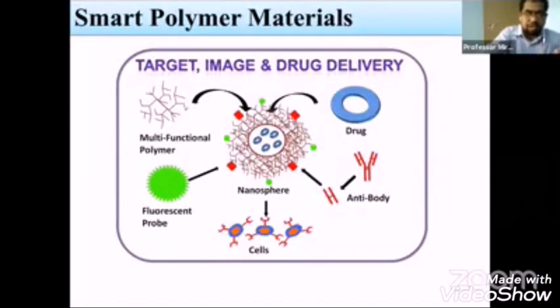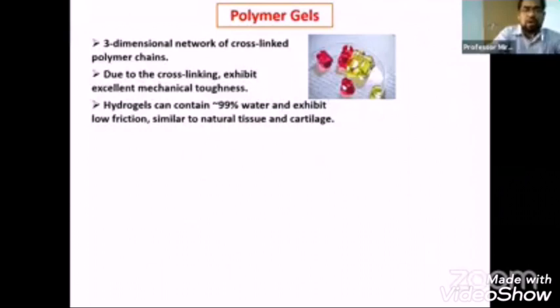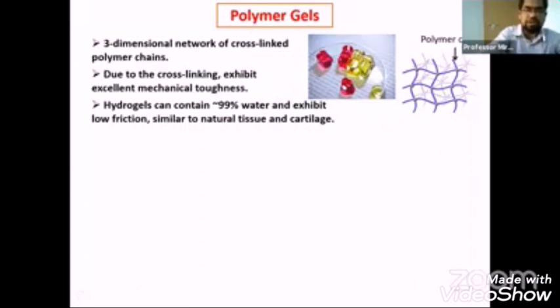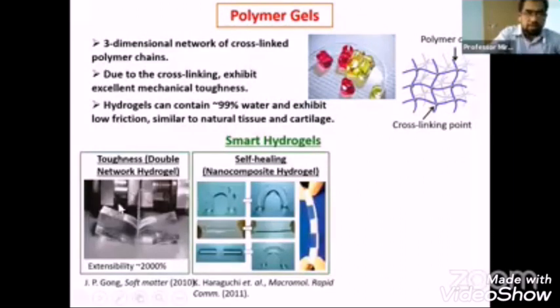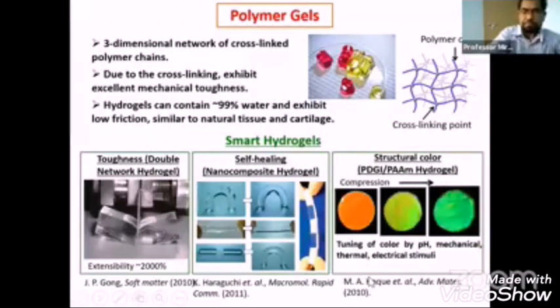This age is also called the age of plastics. There are so many multifunctional polymers, fluorescent probes, nanospheres, cells, antibodies, and drugs, and also polymeric hydrogel, a three-dimensional network of cross-linked polymer chains. You can see here, due to the cross-linking they exhibit excellent mechanical toughness. Hydrogels can contain 99% water and exhibit low friction similar to natural tissue and cartilage. You can see on the left a double network hydrogel which contains 99% water but is very tough. In the middle is a self-healing nanocomposite hydrogel, and on the right they even change the color due to structural color by changing pH,